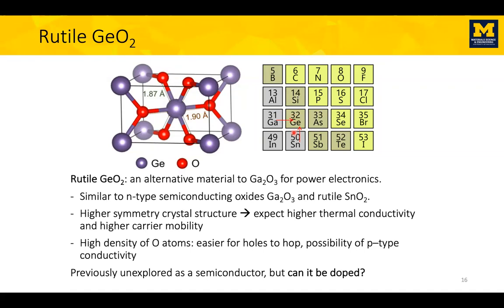It also has a high symmetry in the crystal structure, so we expect that it will conduct electricity and heat very efficiently. And also, it has a higher density of oxygens. The reason for the oxygens is that the valence band is made by the oxygen orbitals, so if you have a hole in the material, it's on the oxygen atoms. So it is easier for those holes to hop from oxygen to oxygen and give you p-type conduction. And if you look at the literature, this material has never been explored as a semiconductor. The question is, can it be doped?